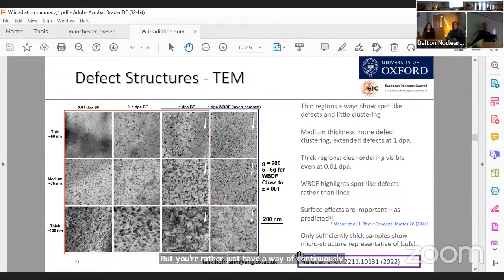The problem then is that you're left with a supersaturation of vacancies, and the vacancies have nobody to recombine with. So they're forever locked into the material, unless you go to high enough temperature that you can get some vacancy removal. There was a really interesting discussion at MSCT about this, and one suggestion was that if you could move to materials that have really high migration barriers for your vacancies and your interstitials, that might be one way of having a more radiation resistant material, counterintuitively enough,